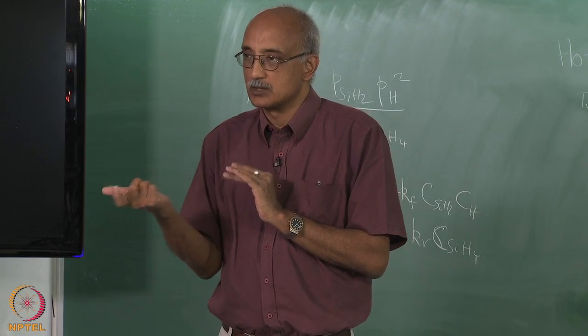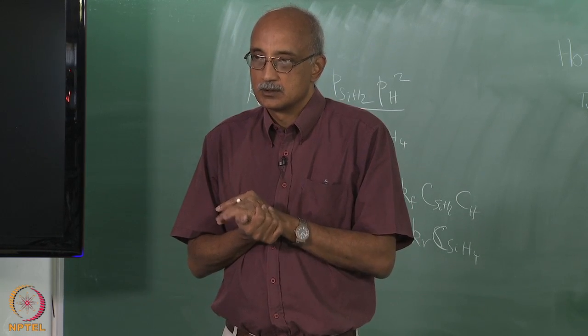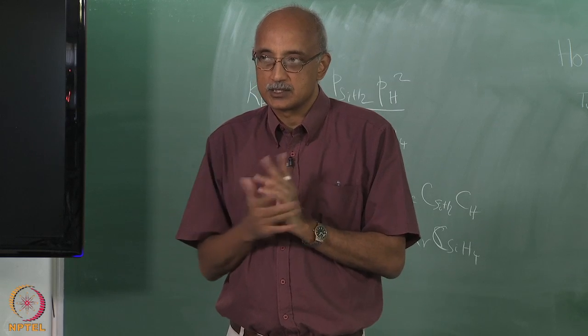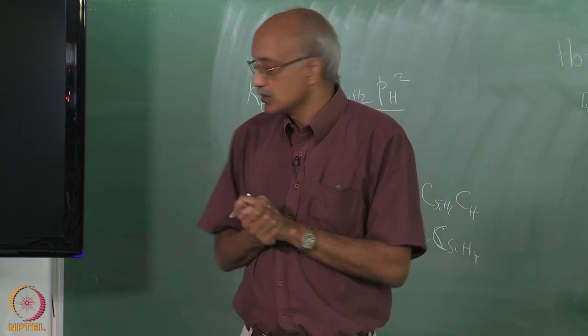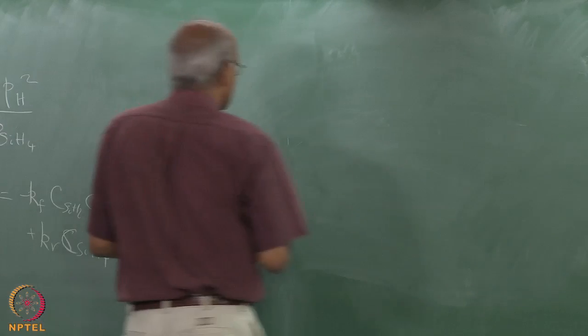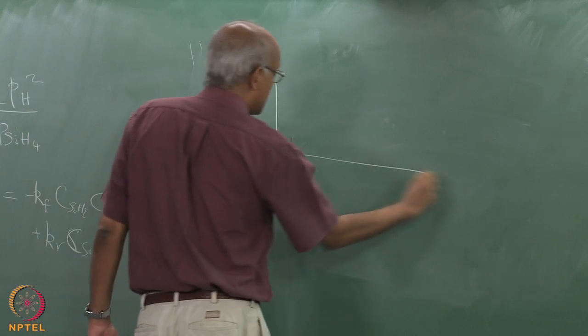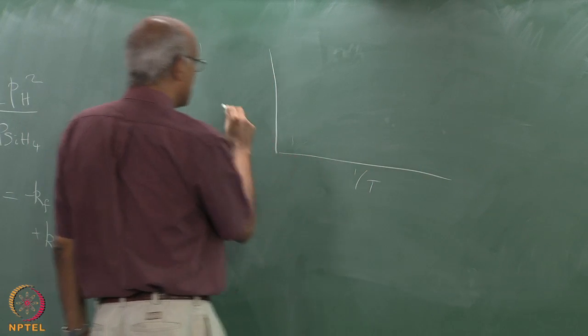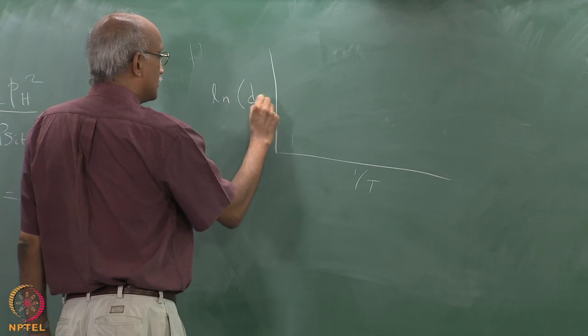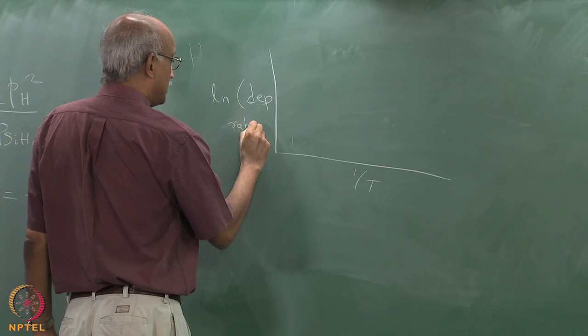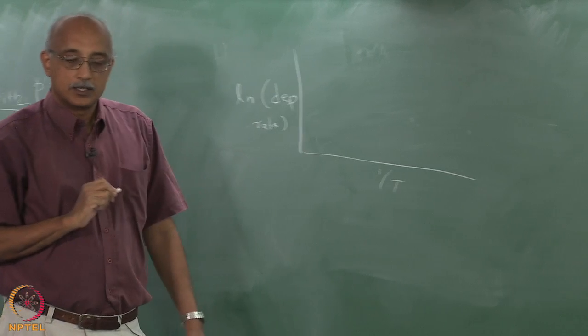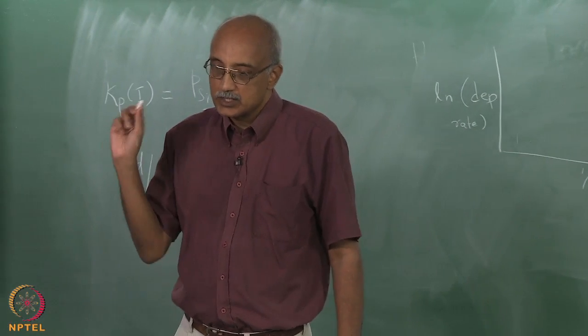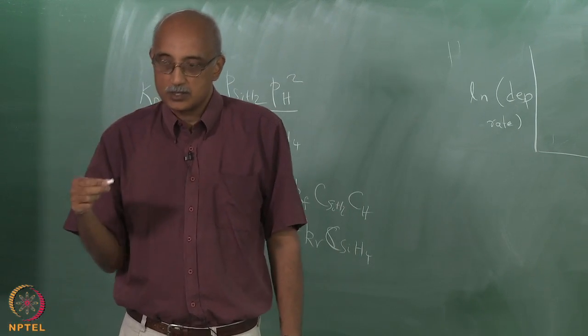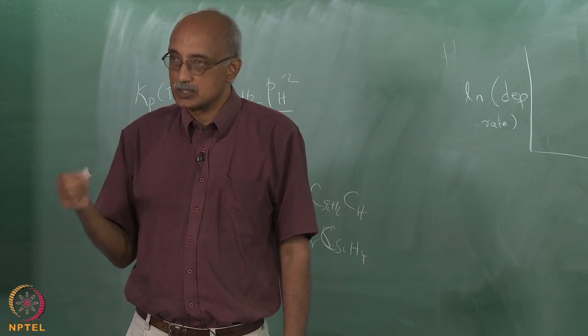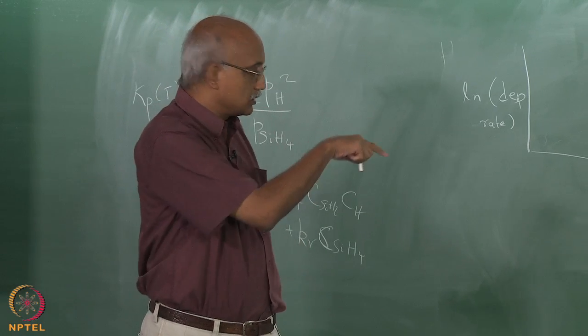Okay, a much more direct test would be to vary the temperature and look at the rate of deposition of the film, right? Much more functionally relevant also, because that is ultimately what you care about. So suppose you do that experiment and you plot 1 over temperature versus the logarithm of the deposition rate in a CVD reactor, in which a higher temperature is more favorable to the formation of a deposit. How do you think this curve will look?